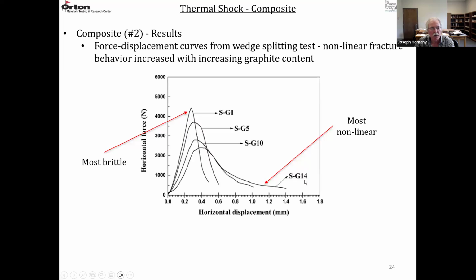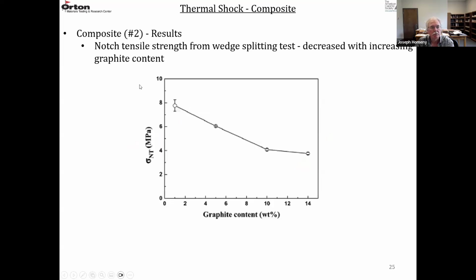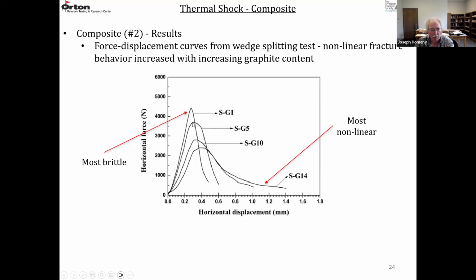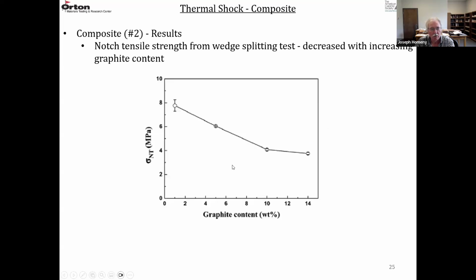So these curves really change as you increase the graphite content. So just looking at these curves, you would say going from SG1 to SG5 to SG10 to SG14, in that order, those should be more thermal shock resistant as you go up in graphite content. This is the notch tensile strength sigma NT from the wedge splitting test versus graphite content, and you can see the strength goes down. We saw that from the maximum in these curves here. So they get weaker with higher graphite content.